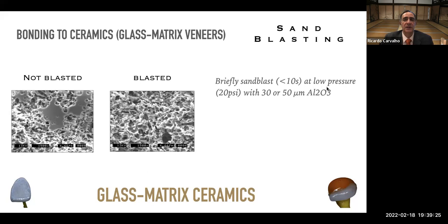And we also are expected to use low pressure because ceramics, particularly the glassy matrix, are very brittle, as we all know. And it's quite easy to break them if we don't take care, if we use a lot of pressure or different size of particles. So the recommendation is, when you have to sandblast, to use this kind of procedure.